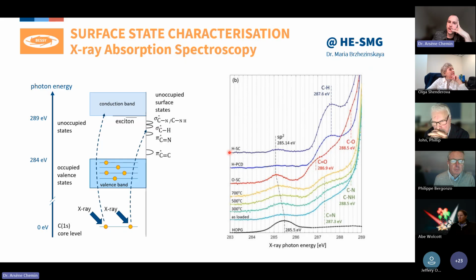If I take, for instance, the H single crystal reference here, you can see a small feature at 285 eV and a much larger one at 287.6 eV. Those two are unoccupied surface states. The first one is the sp2 surface reconstruction, and the big one is the unoccupied surface state quite high in the band gap. By doing so, we can also position the oxidized surface groups, the double bond and single bond oxygen, and we did exactly the same with the nitrogen. You can see that the nitrogen states are slightly shifted up in the band gap compared to the oxygen.